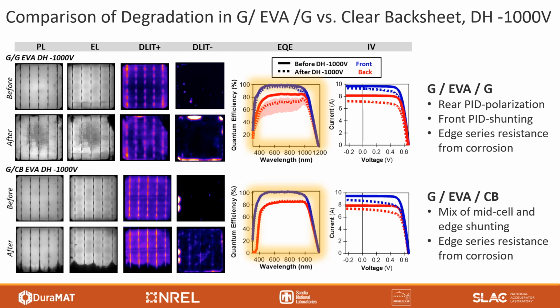In the glass-glass sample, we do see a drop in the EQE for the rear side after stress, and I'm attributing that to a rear side PID polarization effect, which also shows up in the PL and EL images as a dark splotch near the center of the cell.